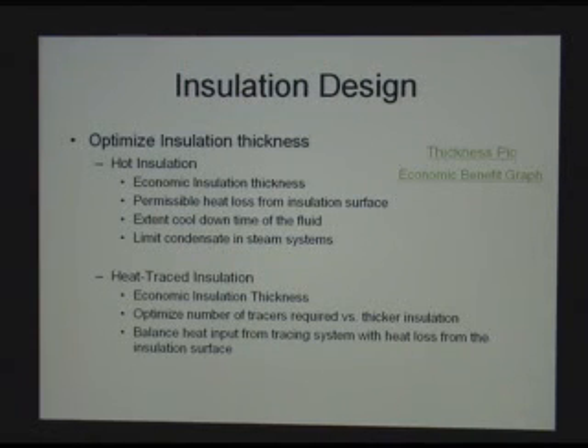Quite often we have to limit the heat loss to a certain value from the insulation surface. Another optimization is to extend the cool down time of the fluid that is being insulated in a pipe or a vessel, and we have to limit condensation in steam systems. On heat-traced systems, it's the same type of thing. In addition, we can optimize the number of tracers versus a thicker insulation. So in some cases, you might want to insulate thicker and save a tracer and be overall ahead. And on this heat-traced system, we have to balance the heat input from